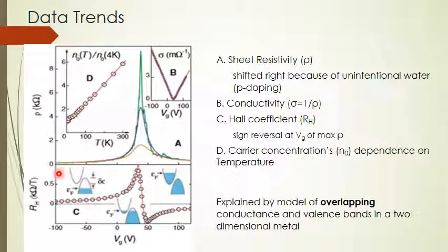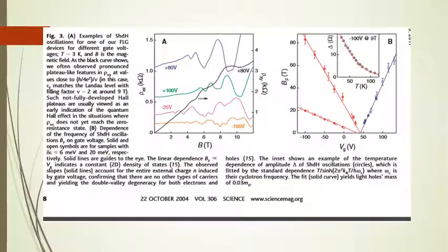This was found to be independent of absolute temperature, therefore indicating the limitations imposed by scattering. The average free path was 0.4 micrometers, and the high carrier mobility is consistent with previous studies in which intercalated graphene with charged dopants in close proximity to graphene resulted in high carrier mobility as well.